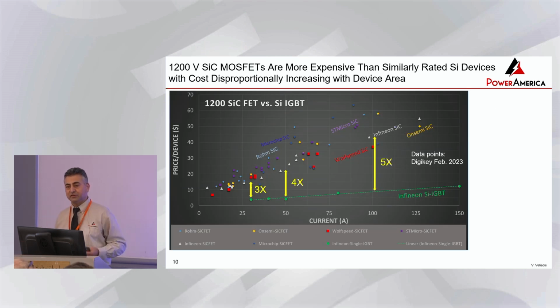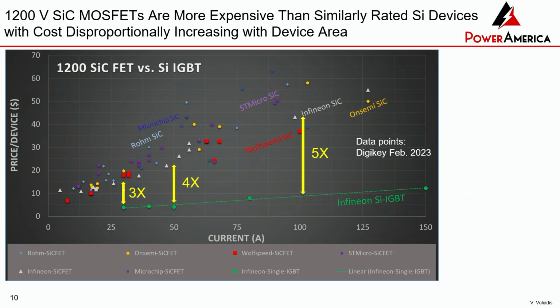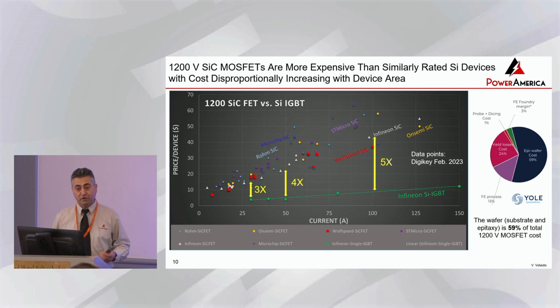All right, so some of the items that I mentioned, one of them was the high cost of silicon carbide devices. And you can see here that the devices in silicon carbide are obviously more expensive than those of silicon. And roughly speaking, at the lower current levels, lower power, they're 3 times more expensive. Then as you increase the power, they go up in cost. And that's because of the defects, right? The larger you make a device, the more probable it is that you will incorporate a defect, and that will reduce your yields. The cost will go up. So there's kind of a sweet spot as far as the area of the device is concerned. And once you exceed that, you pay more, right? And a big portion of the cost, and I'm sure you all will talk about that, comes from the wafer itself. The wafer itself is anywhere between 40 to 60% of the overall cost, right?